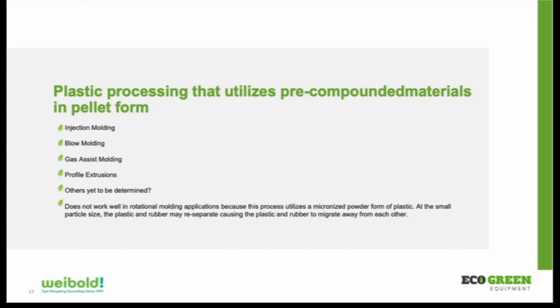very similar to injection molding, where we're going to run the material through a screw into a closed mold. In gas assist, we're actually putting either nitrogen gas into the screw, or we're adding what's called a foaming agent into the screw, which makes the plastic swell up. So this is a type of molding where they're doing very large parts, such as skids or tubs, like animal watering tubs, cattle troughs, and they're able to make very large parts, but with little tiny air bubbles in it to help lighten the overall part.